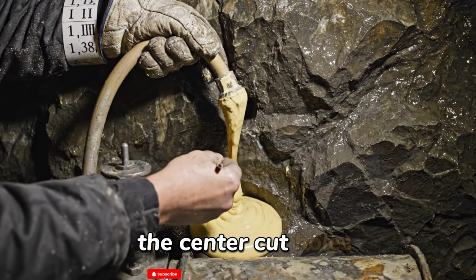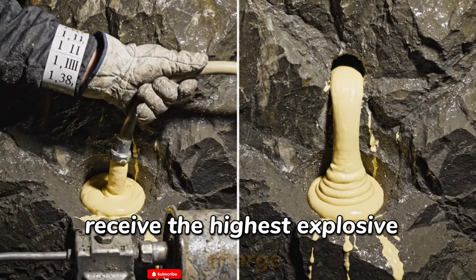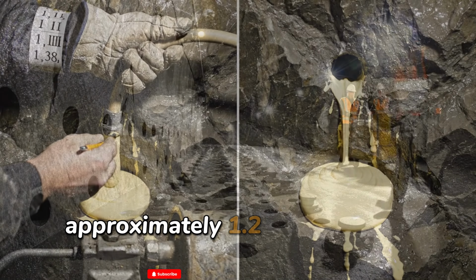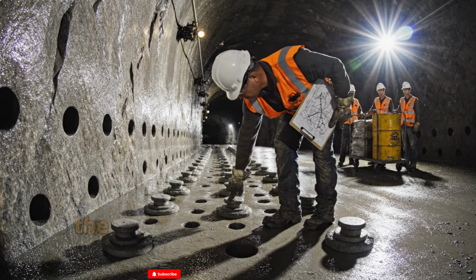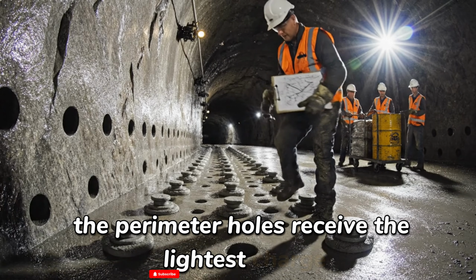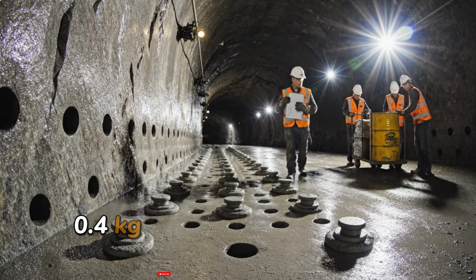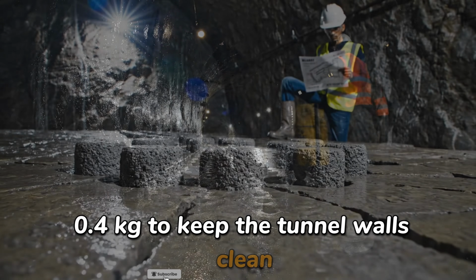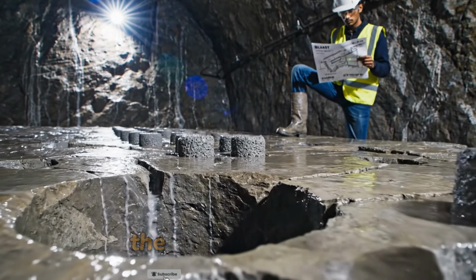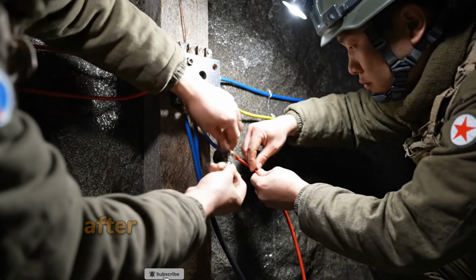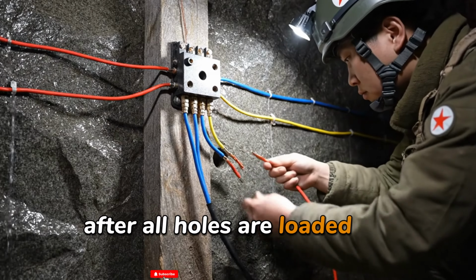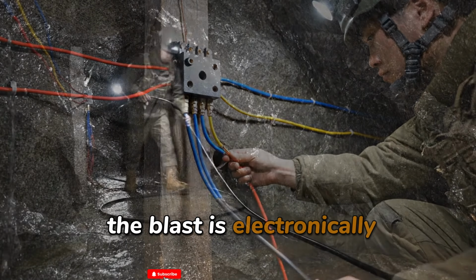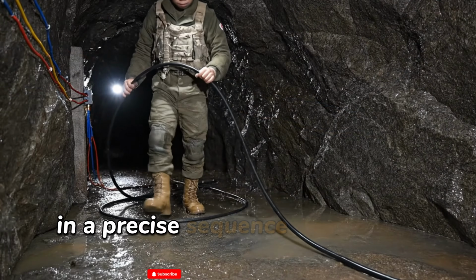The center-cut holes receive the highest explosive charge, approximately 1.2 kilograms per hole. The perimeter holes receive the lightest charge, 0.4 kilograms, to keep the tunnel walls clean and prevent over-fracturing the surrounding rock. After all holes are loaded and wired, the blast is electronically detonated in a precise sequence.